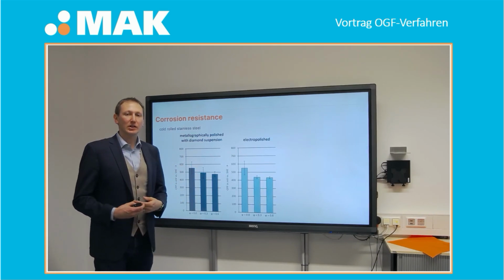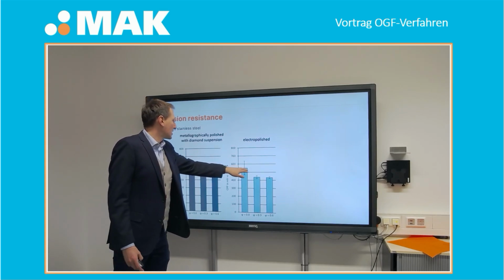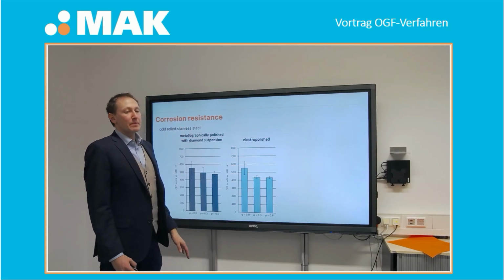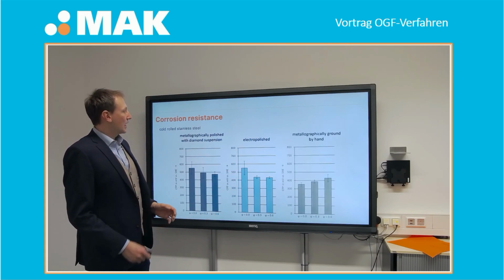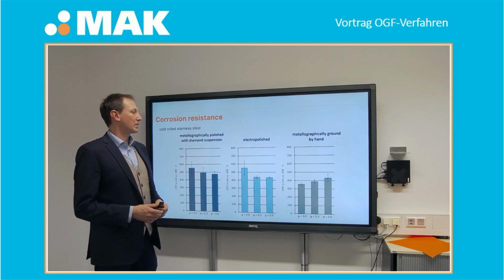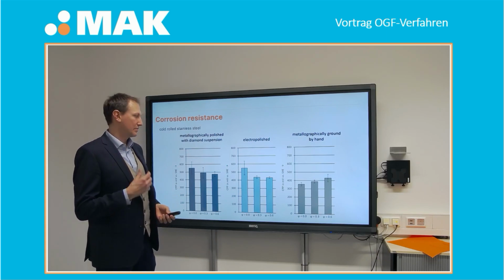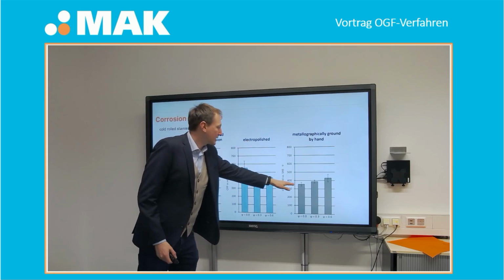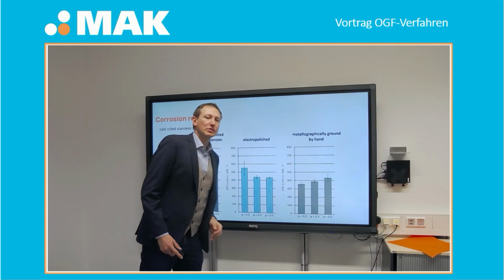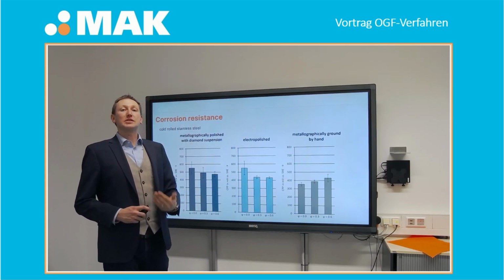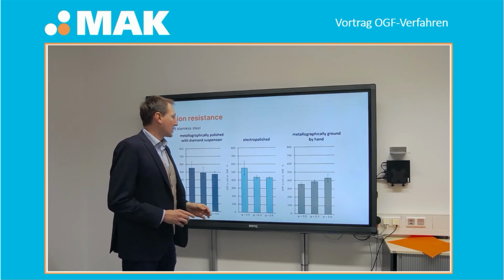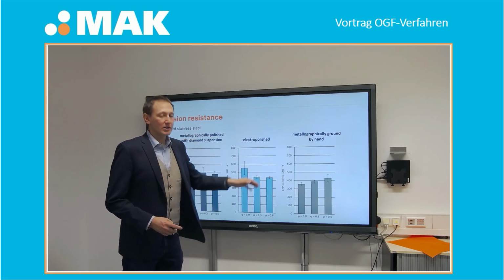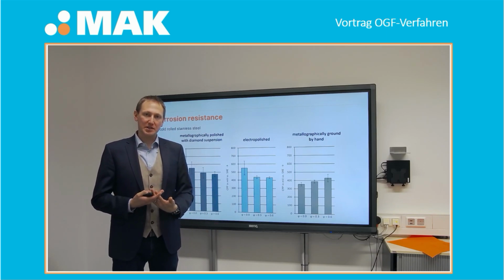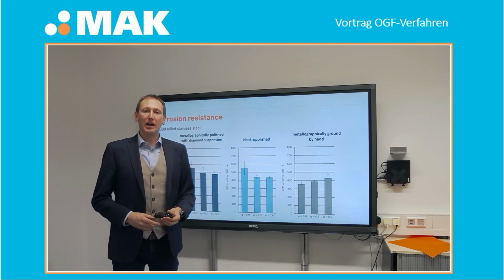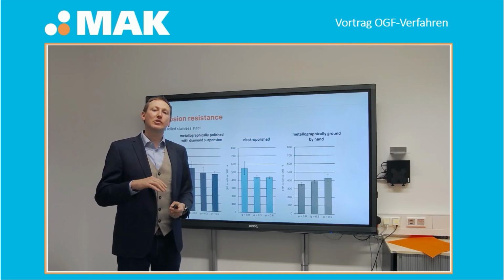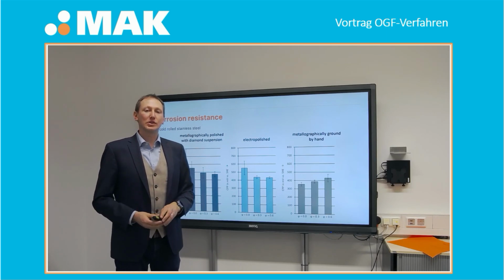If you do some electropolishing on the same kind of surfaces, you also have the decrease of corrosion resistance with an increase of cold rolling. And if we take a look at a metallographic ground surface, so grinding by hand, you can see that grinding by hand leads in this case to a small increase of the corrosion resistance with an increase of cold deformation, which means that you have different effects here, leading to a change in the corrosion resistance. But if you do grinding by hand, you are able to increase the corrosion resistance slightly, even if you have cold deformation.